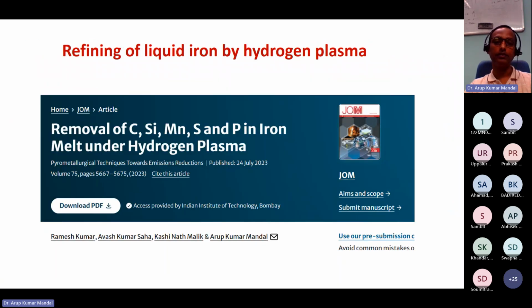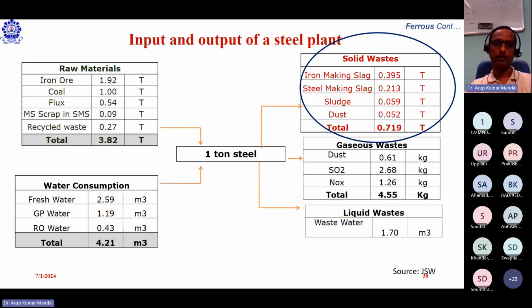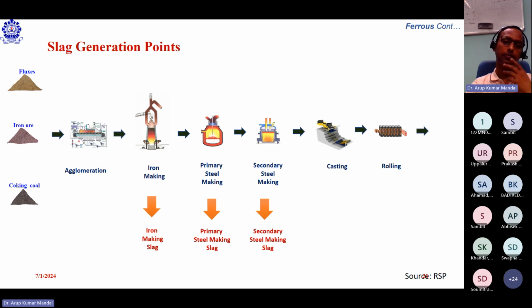So the present topic which I am going to show you is based on this paper, on the removal of carbon, silicon, manganese, sulfur, and phosphorus in iron melt under hydrogen plasma. This is the new concept. In the iron making process, a lot of slag is generated. If you see the source of this slag generation, there is the iron making slag, and primary steel making as well as secondary steel making produce the steel making slag. And this steel making slag is actually for removing the impurities.